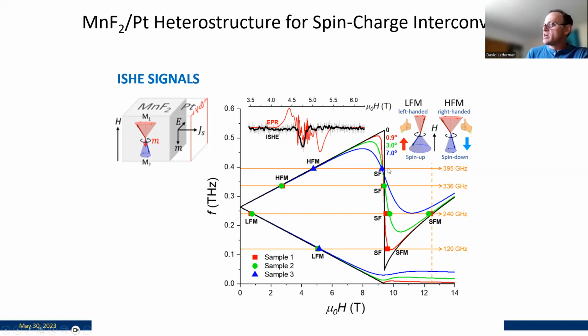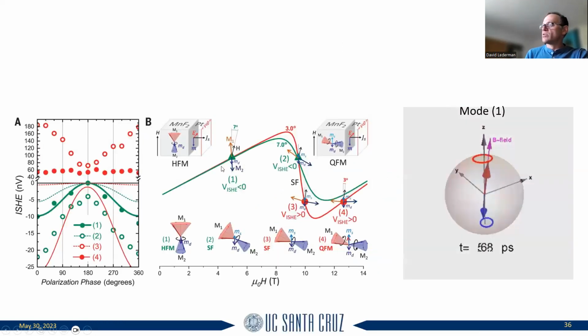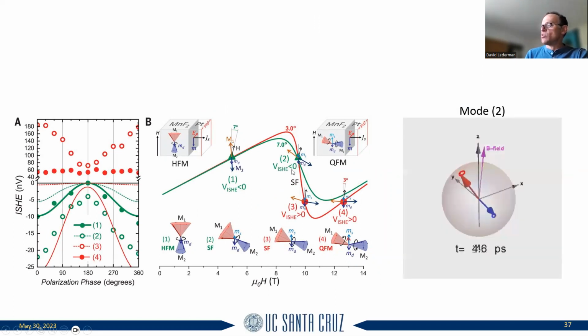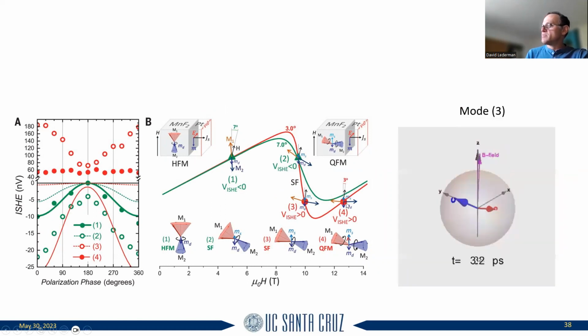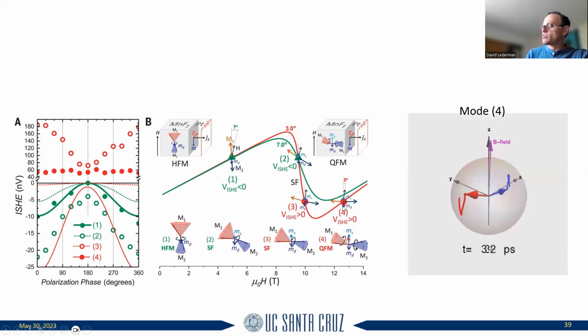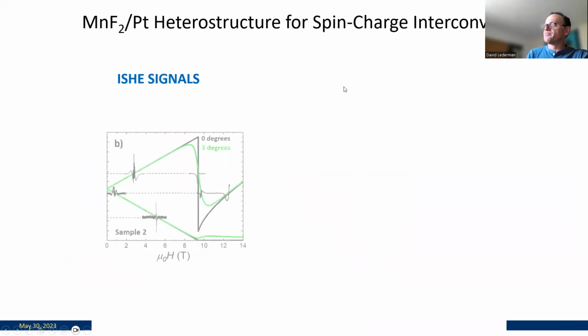So we looked at different modes. Up here you have what's called a spin flop mode. I don't have a lot of time to talk about it, but there's a critical field at which everything turns 90 degrees. That's called the spin flop mode. So we looked at this mode. This is mode number 1 here. This is mode number 2 as a function of field. Mode number 3 looks like this. These are all modes that we were able to detect. And mode number 4 over here. So this is the resonance frequency as a function of field.